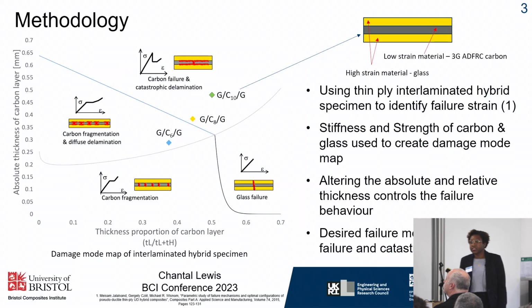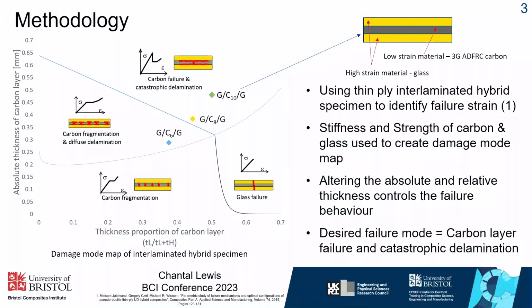So previous research that has been done here at the University of Bristol has shown that it is possible to suppress the premature specimen failure by using thin ply interlaminated hybrid specimens. In this design, the high strain glass material is used on the outside to protect the inner carbon layer, and this helps to minimize the stress concentration in the gripping regions.